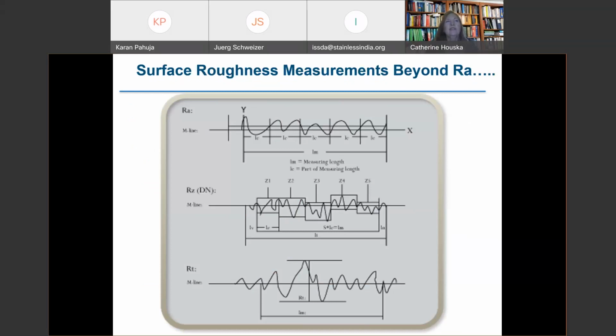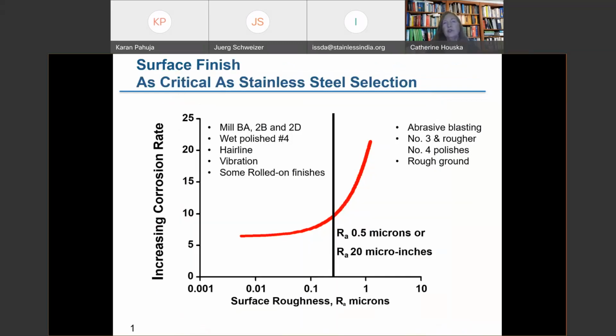I do want to point out that in addition to RA, there are other measurements of surface roughness. For some projects where I'm working with a supplier to try to obtain consistency, RZ can be very handy, and it depends on the finish as to which measurements you might choose, or RT. There are many measurements that can be taken, and it's good for the supplier to understand their finishes and how these numbers might vary so they can obtain consistency as well. RA is also closely correlated with corrosion performance. It doesn't give you 100% prediction, but it does give you a good idea of what might happen.